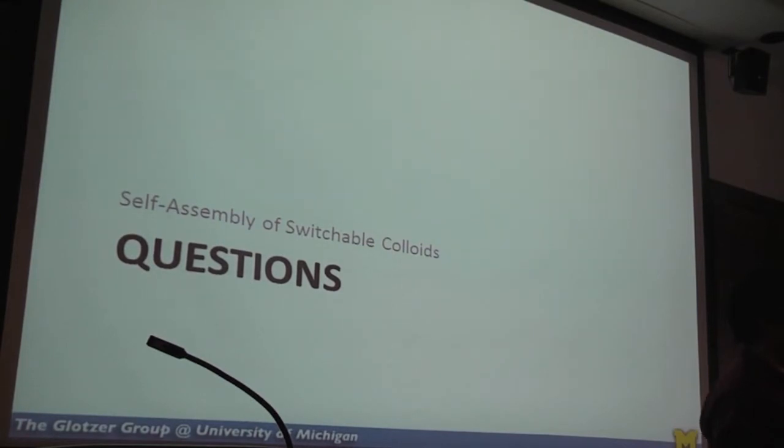So one of them is Monte Carlo, which is stochastic, and you're sampling the configuration space of equilibrium configurations, basically like an Ising model with the switching included. Take a particle here, it disappears and goes randomly to another position. If this other position is more stable than before, you accept this. But in what he's doing, the particles are moving locally according to forces from the other particles. So there are no non-local moves.